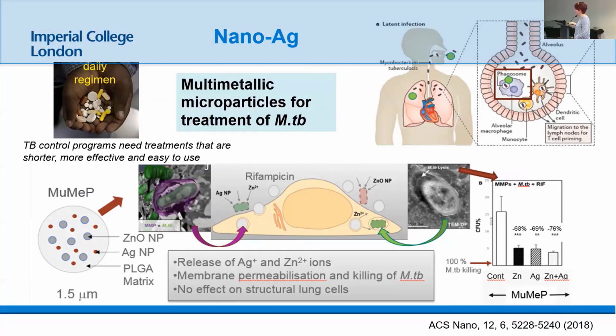And just briefly, what we find here is the nanoparticles, once they're taken up and inside these particles, release both silver and zinc ions. They permeabilize the membrane of the bacteria. So one of the main mechanisms is they make the outer membrane porous, which either directly kills it or makes it much more susceptible to conventional drugs. So drugs that typically are very ineffective suddenly become effective when you combine them with this. But at this dose level, there's no effect on the structural lung cells, because we've done all of that preliminary work to understand the toxicity. And you can see here this huge drop in viability of the TB when you add nanoparticles.